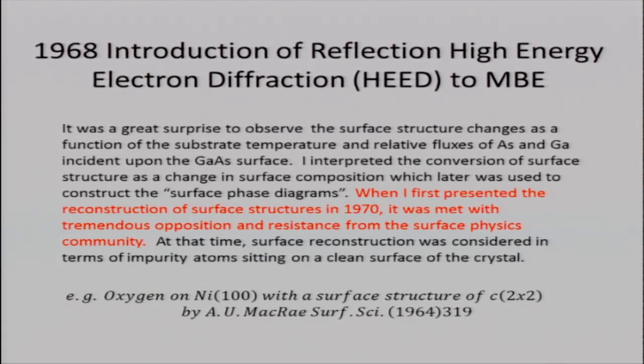It was a great surprise to observe the surface structure changes as a function of substrate temperature and the relative fluxes of arsenic and gallium incident on the gallium arsenide surface. I interpret the conversion of surface structures as due to surface composition changes. And later I used those surface composition changes to plot the surface phase diagram.